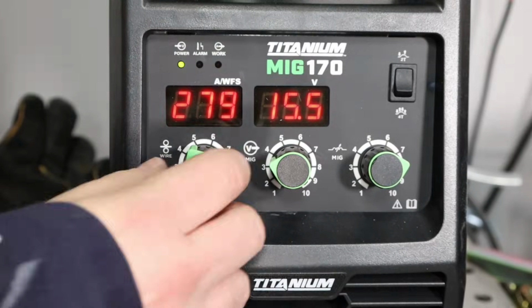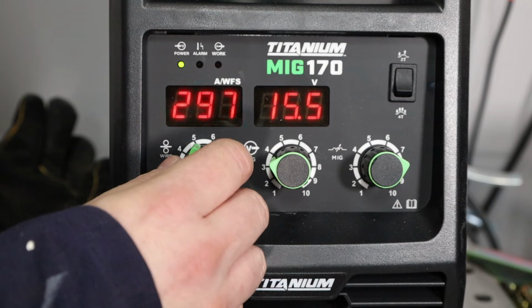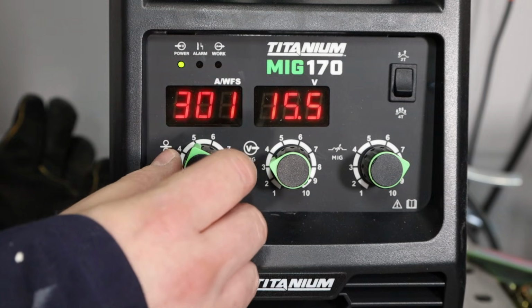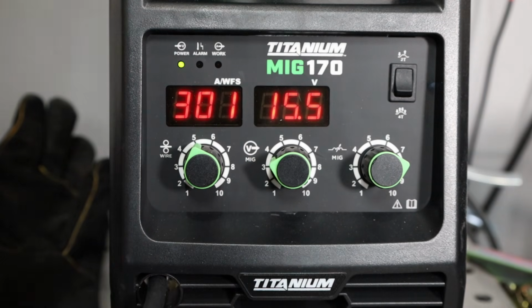On this thin sheet metal, I just set it to the recommended settings. You can see I'm not getting into that spray transfer that I need. I'll watch it one more time, and you can see it's balling up on the wire there. So that didn't work as well as I'd hoped. I did some experiments and ended up with some settings that gave me a pretty good result, but it wasn't in a nice spray transfer like I was hoping for. It's kind of shorting out just a little bit, like you can see here.